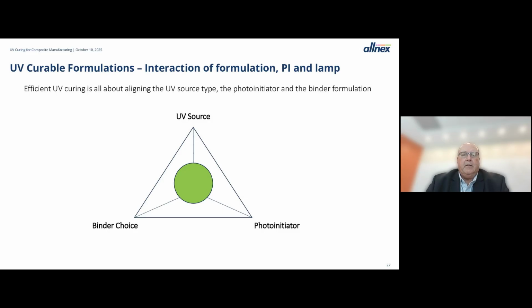And finally, we talked about the binders, the oligomers and monomers. We talked about the UV source, the lamps, and then the photoinitiator. And when you're developing formulations or using formulations, you have to be cognizant of all three. You have to know where your lamps are putting out their energy. You have to know where your photoinitiator is absorbing. You have to know what elements in your binder may compete with that photoinitiator for the UV energy. So all of these things work in tandem. You really don't develop one without thinking about the other two.